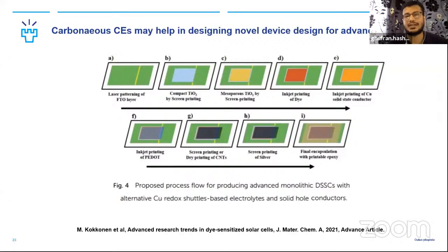And then you can print, similarly to how you produce for the two electrode based device design, the mesoporous titanium layer. And then you can even potentially print the dye through inkjet, and also the copper electrolyte, and then even the inkjet printing of the PEDOT, and then you can screen print either high or low temperature paste based upon the requirement. There are many flavors of both high and low temperature paste available for this carbonaceous material, even commercially. So either you can make it, or you can get it. And then you can obtain the silver contacts, and then you can passivate the whole device design with a printable epoxy. This proposed design we recently proposed in our review article. You can all download it.